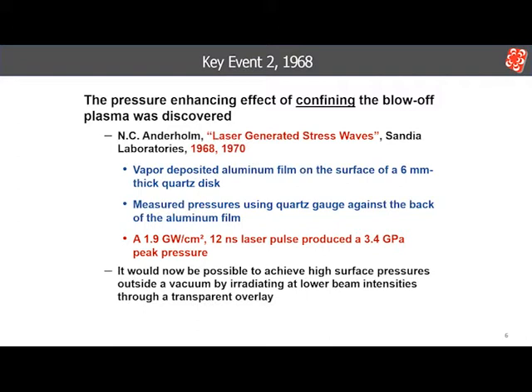He vapor deposited an aluminum film on the surface of a 6 mm thick quartz disc and measured the pressure pulse with a quartz gauge. His demonstration of this concept produced a 3.4 gigapascal surface pressure with a beam power density of 1.9 gigawatts per centimeter squared. The simple demonstration for dramatically increasing the impact of a laser impulse on a surface would eventually enable the development of laser shock peening.